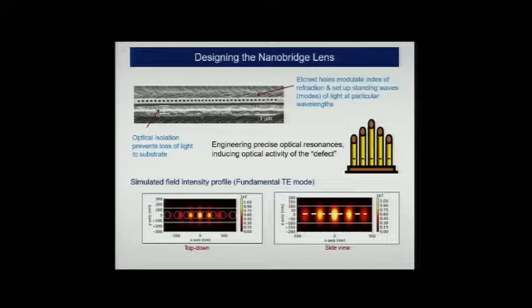What that means is we have an extremely high density electromagnetic field at exactly the resonant frequency of our emitter. And it's designed to be an exquisite switch to turn on the oscillations back and forth of our emitter. In particular, if we look at the high field regions, and if we were able to put our emitter right there at the maximum of the electromagnetic field, then the cavity exerts its greater influence. But as you will guess as we go through here, that's really hard to do.